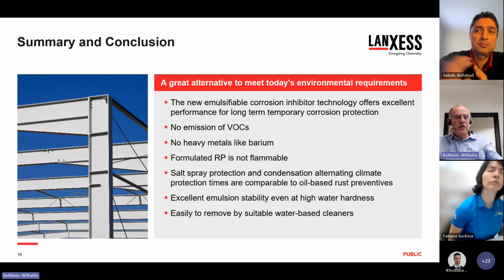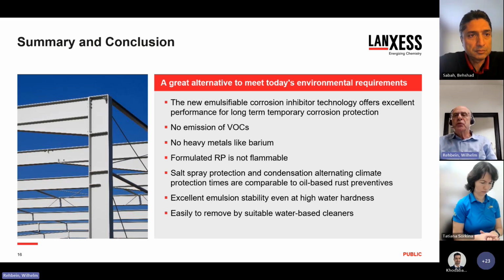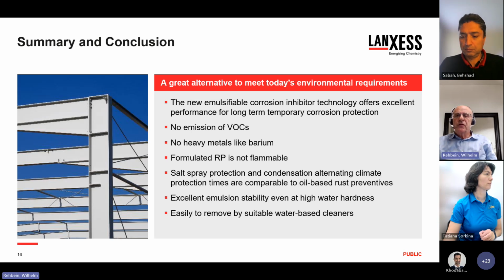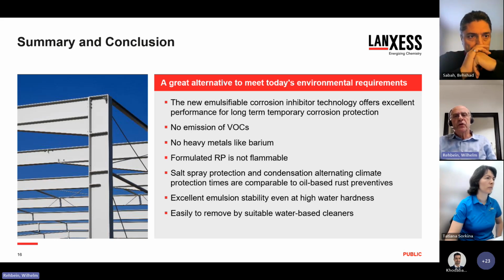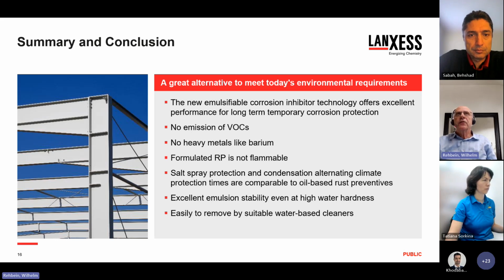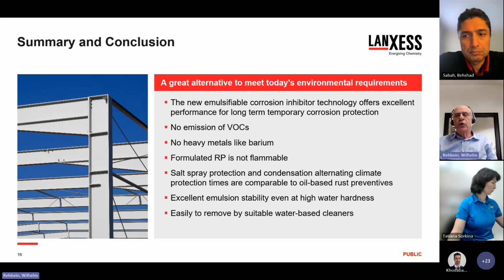First of all, regarding the water quality, we just used tap water to prepare the emulsion, and we also made tests with tap water with higher water hardness of about, as far as I remember, 200 ppm calcium. So the emulsion remained stable even with this higher water hardness. And regarding overseas transport, this always depends on the thickness of the rust preventive film on the parts that have to be protected. But we found that the rust protection performance, for example in the salt spray test, was absolutely comparable to other commercially available rust preventives that are used for overseas transport.